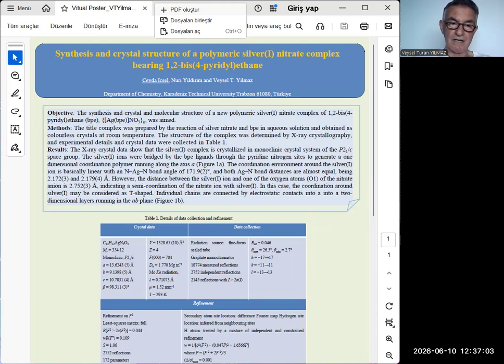This complex was prepared by the reaction of silver nitrate and 1,2-bis(4-pyridyl)ethane in aqueous solution, and we obtained its colorless crystals at room temperature after a few days. We observed that the complex is both air and light stable.